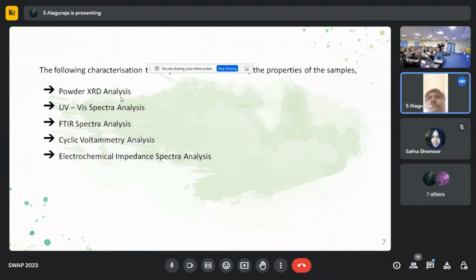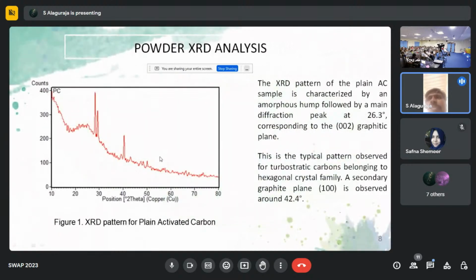From my studies, I have powder XRD, UV visible spectral analysis, FTIR spectral analysis, cyclic voltammetry analysis, and electrochemical impedance spectral analysis. From XRD, the activated carbon peak is the 002 plane, at a diffraction angle of 26.3 degrees, and the secondary graphite plane is 100 at 42.4 degrees.